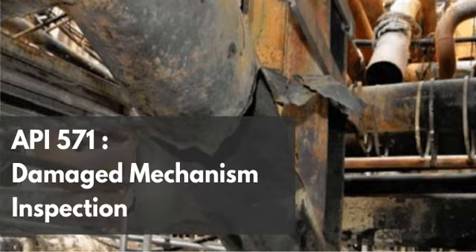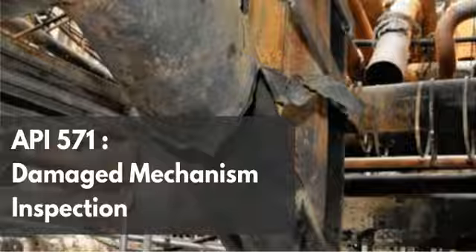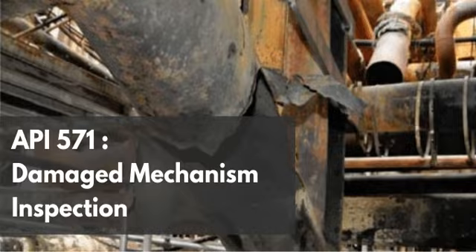Yeah, exactly. Furthermore, austenitic stainless steels form a highly stable, continuous, and impermeable chromium oxide passive layer on their surface. And that passive layer holds up against the amine. Incredibly well. It's incredibly resilient in amine environments. The amine simply cannot initiate the localized dissolution required to attack the grain boundaries. So the thermodynamic driving force for the crack initiation is just neutralized. Completely neutralized. Now, the text specifically mentions clad stainless steel as an option too, which is a critical economic and engineering reality. Oh, for sure.